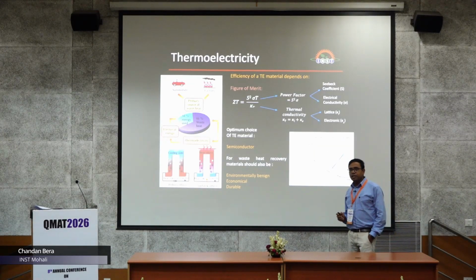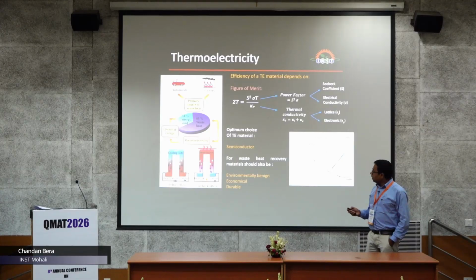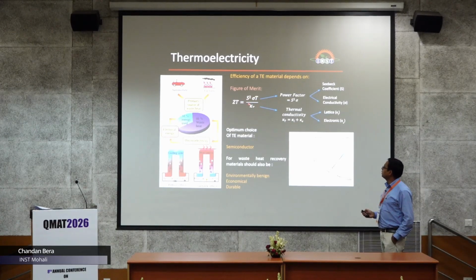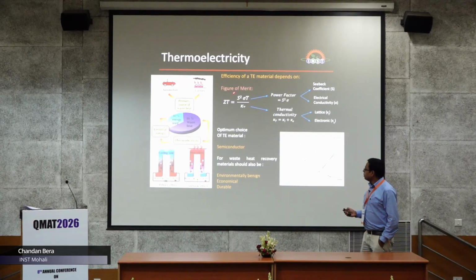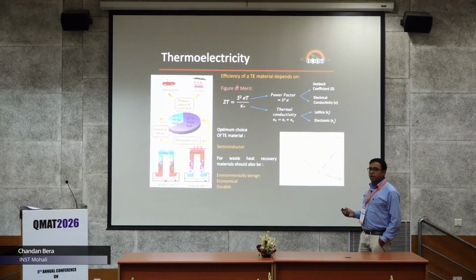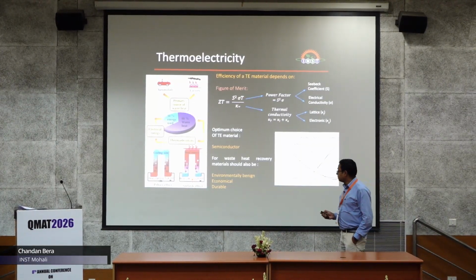The thermoelectric figure of merit of a material is defined by this ZT, the figure of merit, which is related to the Seebeck coefficient and electrical conductivity, and inversely proportional to the total thermal conductivity. We multiply both sides by T to make the figure of merit dimensionless.